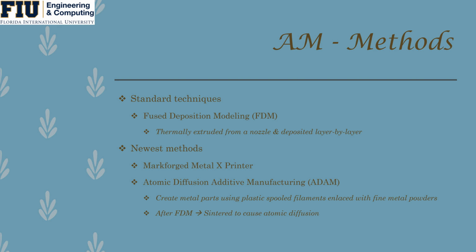One of the newest methods in the AM industry can be seen through Markforged's Metal X printer. They are using atomic diffusion additive manufacturing (ADAM), in which they create metal parts using a plastic spooled filament that is laced with fine metallic powders. They use this filament to create the part using the FDM method layer by layer, and then the part is sintered to cause the atomic diffusion.